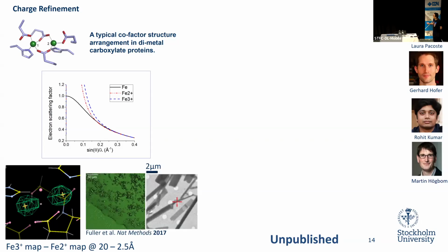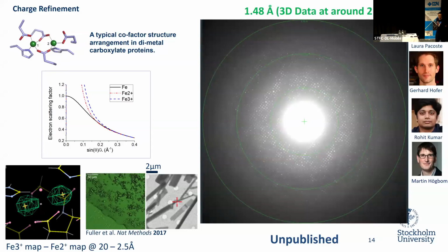So these are actually the crystals our collaborator used for the XFEL experiment, and we could collect the electron diffraction data up to 5 angstrom from this crystal, and they are slightly too large for us. So using Gary's method, we can produce these very nice thin plate or needle-like, ribbon-like crystals, and this is what resolution we can get. But after playing with the data, I think we see more problems than getting answers.